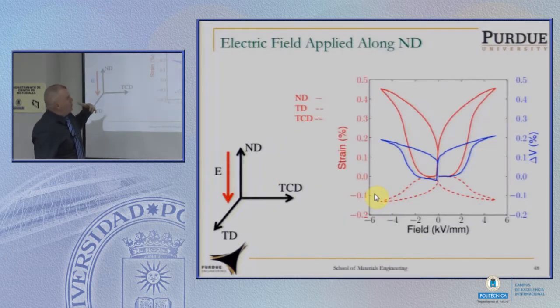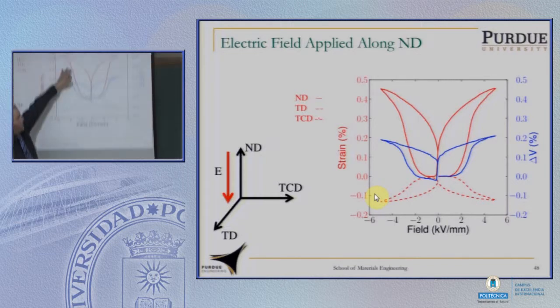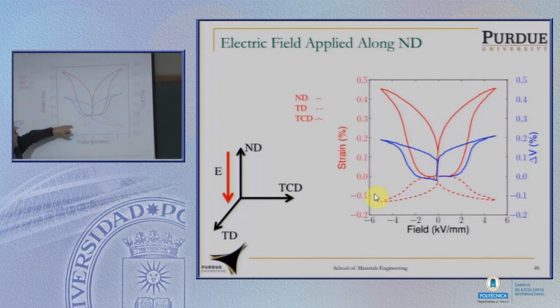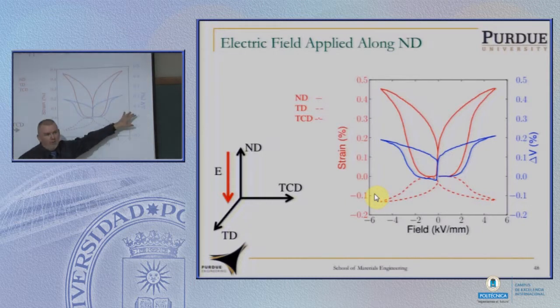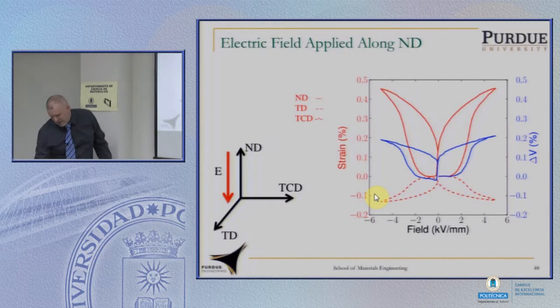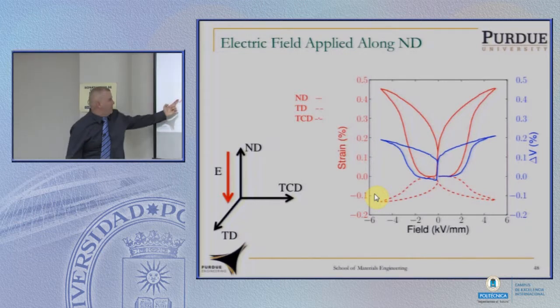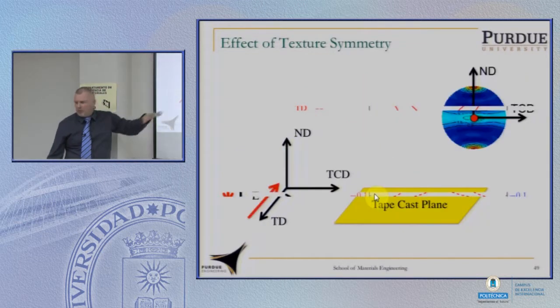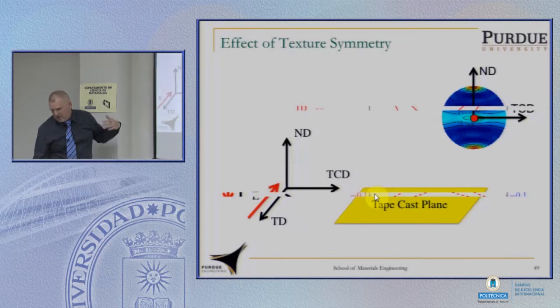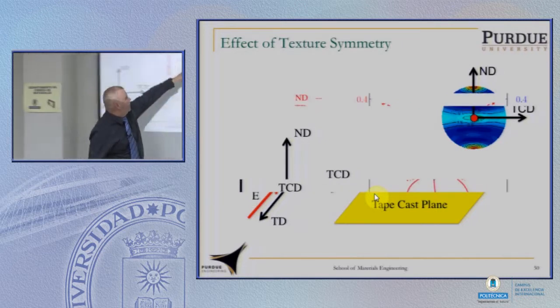Okay. So the strain measurements that are shown here, this is the strain measurement in the direction of applied field. This is the strain measurement perpendicular to it. And this is the strain in terms of volume. So the volume is shown here. Okay. So we were able to show those materials and show that there's a difference. In this case, we applied electric field across the actual tape casting plane. And you can see that this is the direction of the applied field.